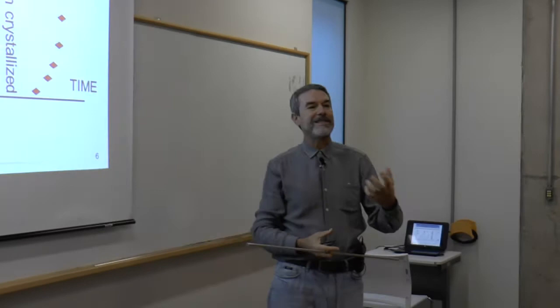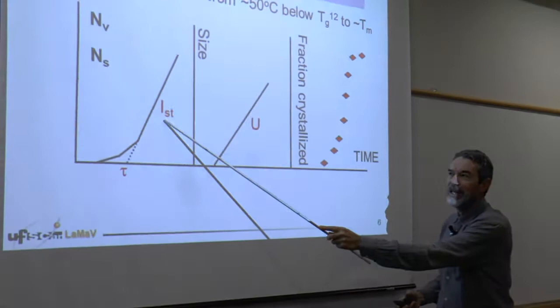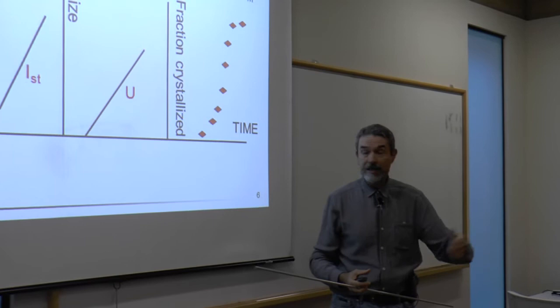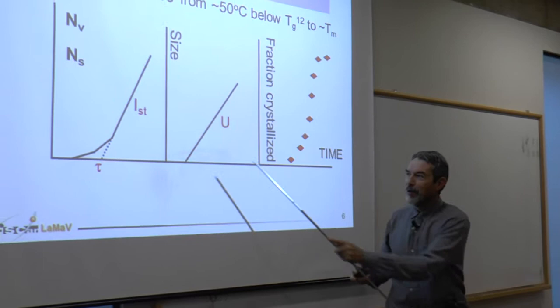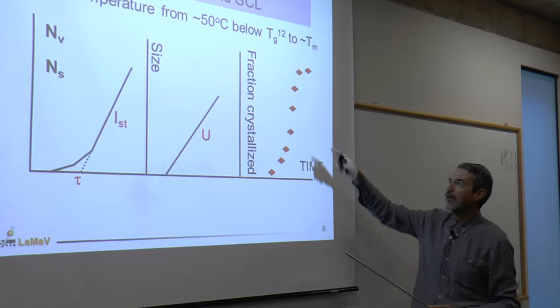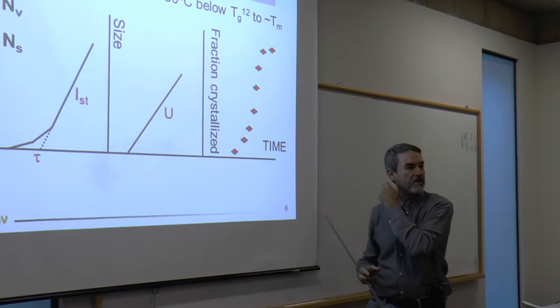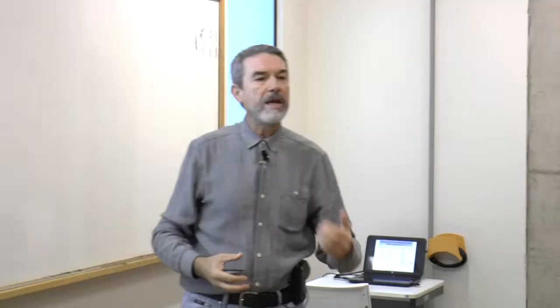Consistency test. And the three final exercises I'm going to give you for your homework will be to get nucleation rate data, then test the theory for your adopted glass. Then you're going to get crystal growth rate data for your adopted glass, test the theoretical models, and then with nucleation rate and growth rate, you're able to calculate the overall volume fraction crystallized, and from the volume fraction crystallized, estimate the so-called critical cooling rate for glass formation. In other words, how fast you have to cool down a glass forming liquid to avoid crystallization or to make a glass, to vitrify that liquid.